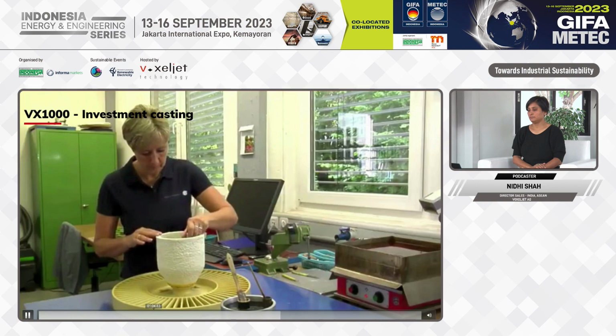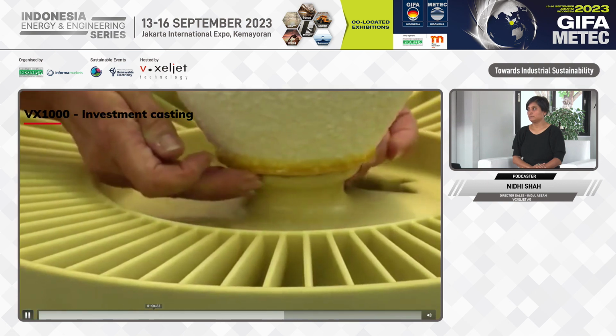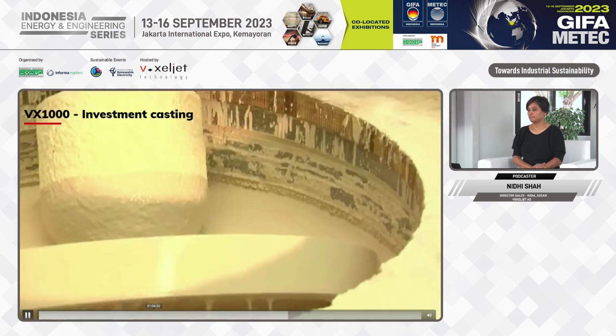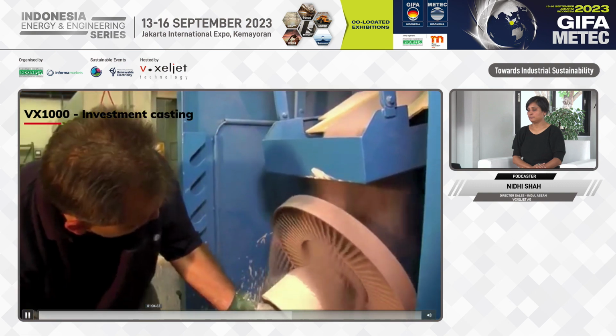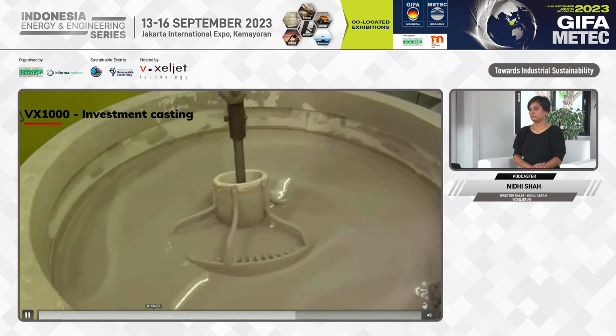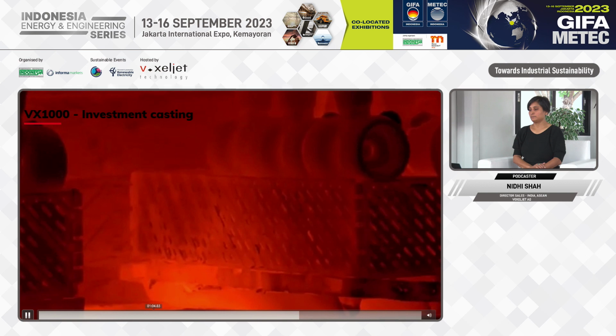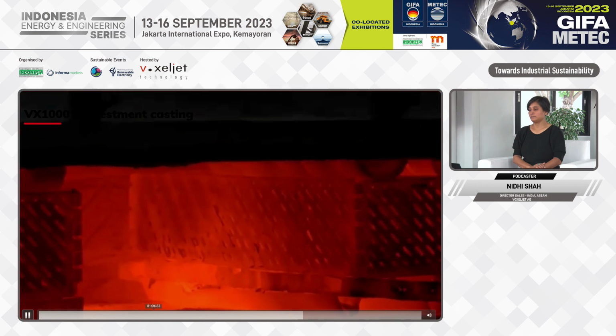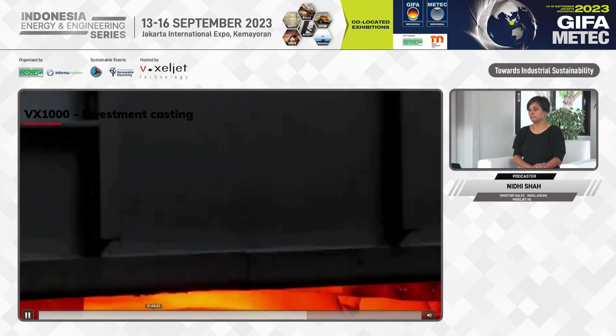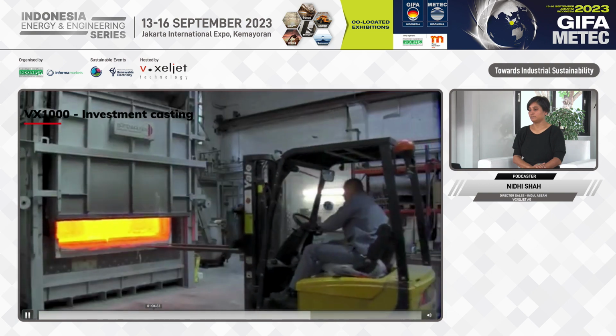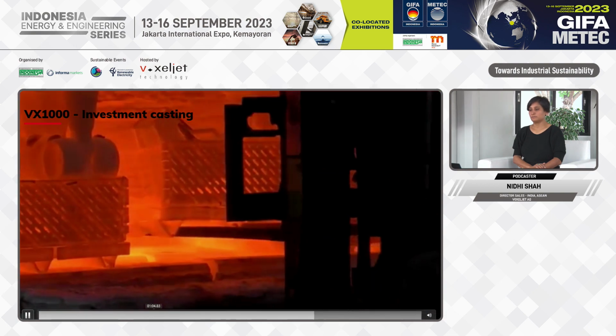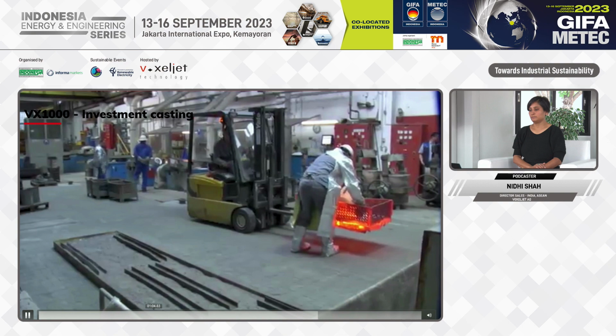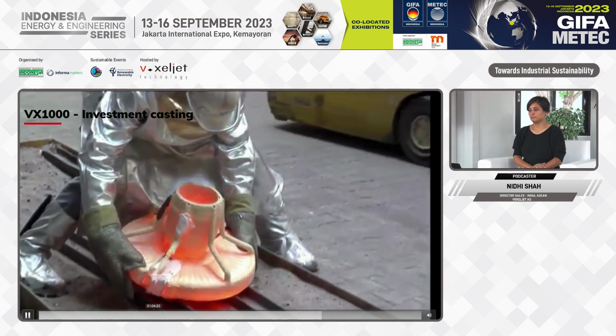The finishing process is the same as for conventional wax models. The first ceramic coatings are applied manually, while subsequent layers are added by a robot. The plastic models soften at 80 degrees C and shrink, so that tears cannot form in the ceramic shell. Finally, the 3D printed model is burnt out from the casting die in the kiln. The plastic models burn out with virtually no residue.